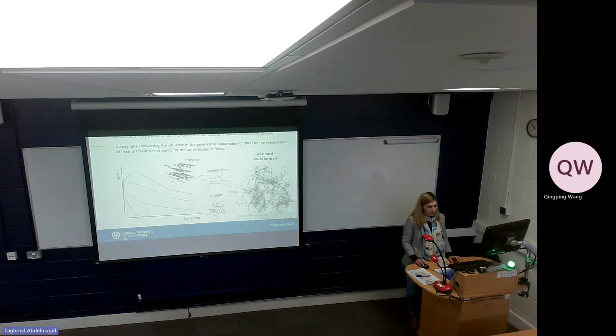But when we have fibers like this with various length, it works like a hybrid mix. So it means that the smaller parts can attract the smaller cracks, and the bigger can attract the bigger cracks. And please remember that, for example, when we use 1% of the big crimped fibers, it will mean that we will have some number of fibers inside the concrete. When we put the steel cord, we have much more of them. So the mix is much more homogeneous, because we may not have too many big fibers, but generally in the concrete we have a lot of wires, and it is all over there.